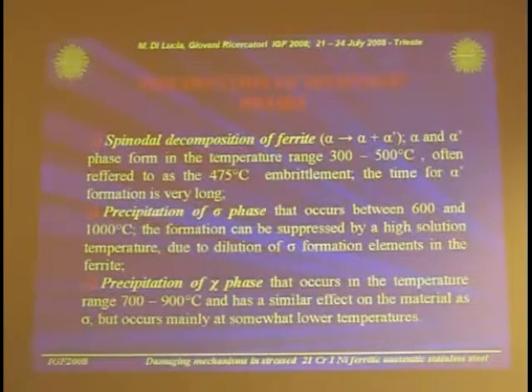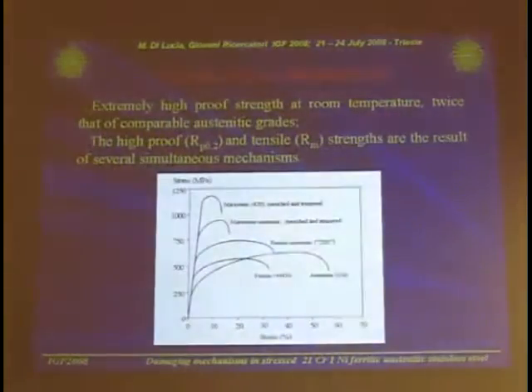With respect to precipitation of secondary phases, there are three different temperature ranges. With respect to mechanical properties, an important characteristic of the duplex stainless steels is their extremely high proof strength at room temperature, twice that of comparable austenitic grades. The high proof and tensile strength are the result of several simultaneous mechanisms. The following figure shows the sigma-epsilon diagram of different kinds of stainless steels.